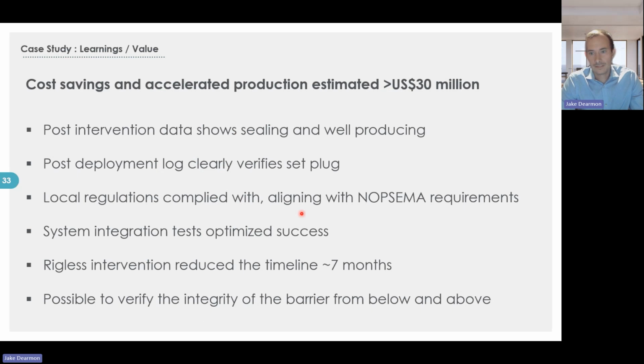So some of the learnings there: there's tremendous financial benefits to the client, over $30 million saved compared to a hydraulic workover unit, plus the time waiting for that. Post-deployment log clearly saw on acoustic and gamma ray that we had a good plug. The SITs were completed with V0 testing after several iterative testing with different heater designs we had done at BiSN. Saved about 7 months on getting that well back online compared to waiting on a hydraulic workover unit.